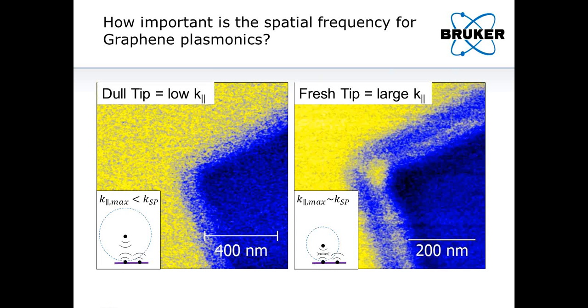For the last slide, I want to show the effect of the tip radius and how that's connected to the spatial frequencies generated on the graphene surface. On the left, you see an image taken with a dull tip, which corresponds to a low spatial momentum, a low spatial frequency. On the right, I show a fresh tip image, which has a large spatial momentum.